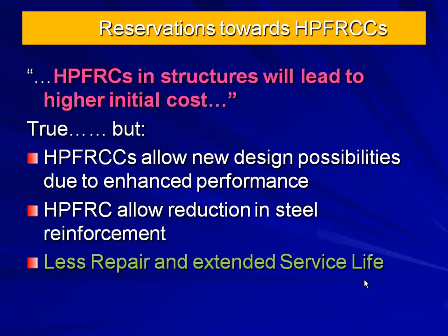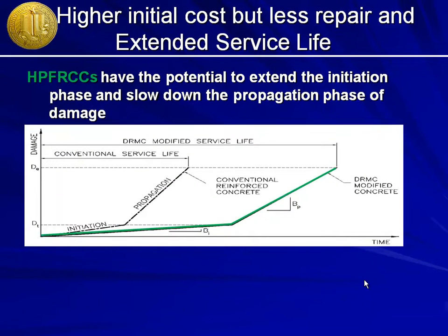You will have less repair and you have extended service life. And I want to go back to that one very briefly. This is your damage as a function of time, and this is your initiation of the damage, that's the propagation. And this is your service life right here. What we can do with hybrid fiber reinforced, we can do two things. We can extend the initiation phase, and we can slow down the propagation phase. So your final service life is this one right here, not anymore this one right here.